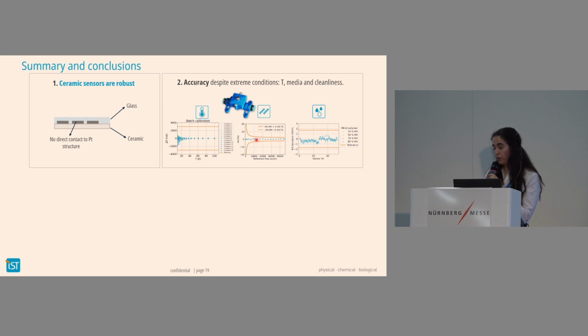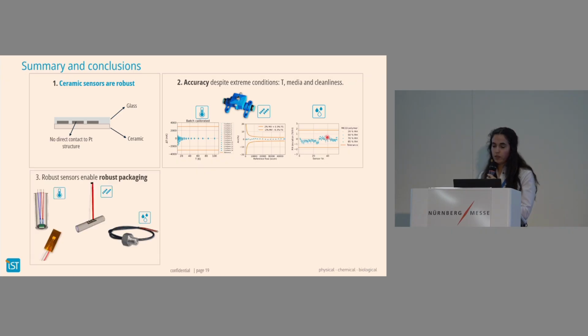We saw that for flow, for the FS module, where the accuracy was still very good, also despite different temperatures or different pressures. And we just saw now for the MK33, which was able to measure over extremely long periods of time and was also able to deliver good accuracy after a temperature stress test. This robust technology enables then robust packaging.